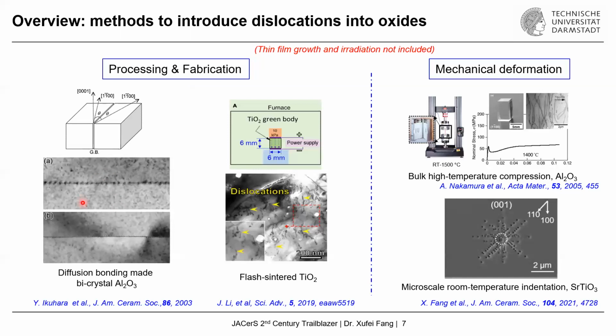For example, here is a bicrystal alumina fabricated by thermal diffusion bonding. Simply put, you take 2 single crystals and bond them together with a specific tilt angle or twist angle. You will be able to engineer edge or screw type dislocations at the grain boundary. By the way, this is the grain boundary, and the dislocations are actually threading into the screen in the 3D dimension.